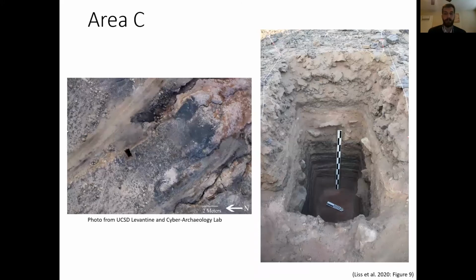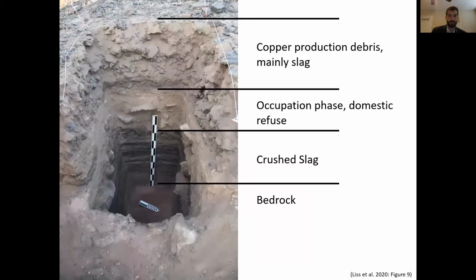Moving on to the slag mound excavation, we selected this slag mound on the southeastern edge of the site, partially because it had already been damaged by a modern road. You can see this in the picture on the left with the road in the top left corner there. And we just did a small 1 by 1 meter probe into the slag mound. You can see this in the picture on the right.